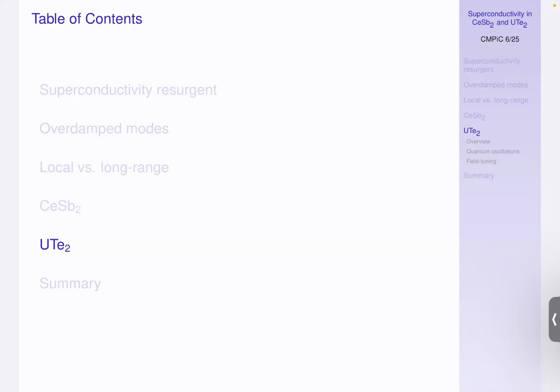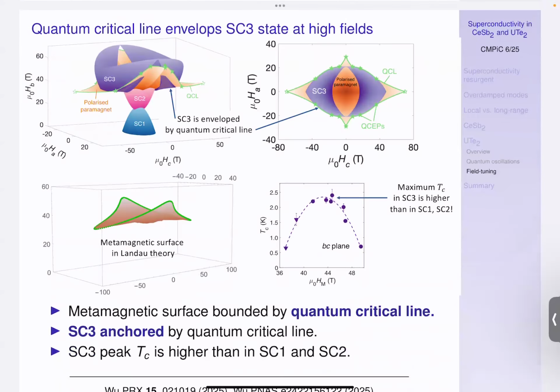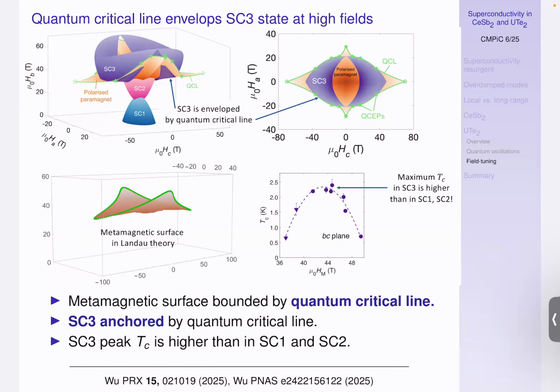That's okay. What I can do is that's actually very good because we have in the audience Tony, at the back, and he's going to talk about UTe2 this afternoon. I think the main point there I was going to make is just like through a series of very beautiful high field measurements, Tony and Alex and other colleagues from the group have mapped out the magnetic phase diagram for UTe2, which shows how, in low fields you have SC1, the higher fields superconducting state 2, and then at very high fields, the superconducting state 3, which sits sort of, if you like, above the metamagnetic ceiling.